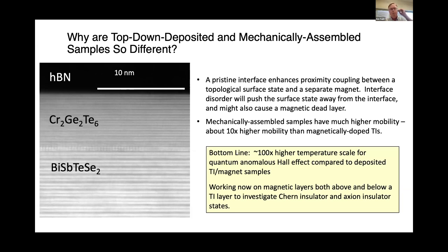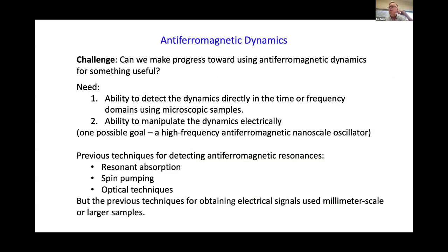Also, compared to magnetically doped topological insulators, these exfoliated samples have much higher mobility, about 10 times higher mobility. That might make a difference too. So far, we've only done magnets on one surface of the topological insulator. It would certainly be interesting to have them on both sides. We're working on that, but this is as far as we've gotten so far. So that was my first story.